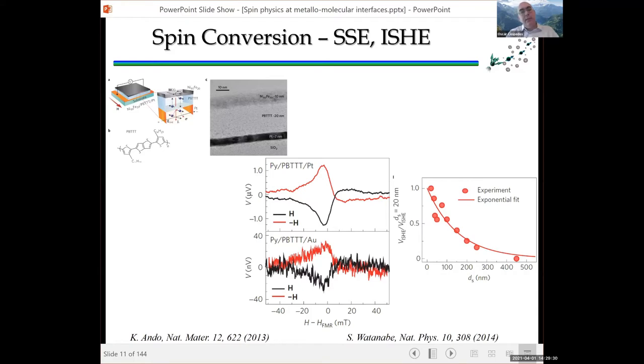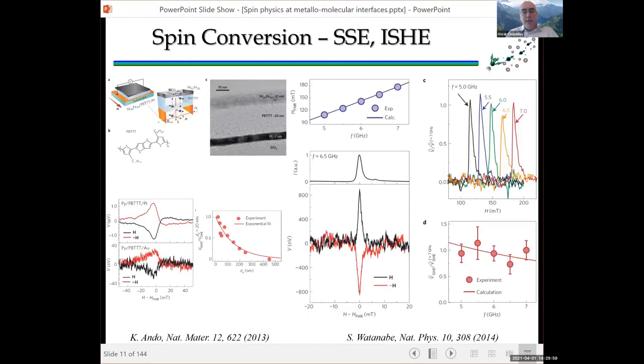And what they could see is that this PBTTT polymer could still transport the pure spin current that will be detected then by the platinum. The signal obviously decays depending on the thickness of the PBTTT layer, but you still can observe that inverse spin Hall effect for up to 250 nanometers of polymer, which is quite remarkable. And then they did the same thing for PEDOT:PSS, which is a very typical polymer for organic solar cells. And again, they had the same effects. They could correlate it this time with the magnetic field and the frequency used to generate the FMR and the spin current. They think that they have a spin current and an inverse spin Hall effect that is inversely proportional to the field and the frequency. It could be argued perhaps that this could also be fit with a flat linear dependence, a constant essentially, but nevertheless, that's what their calculations show.